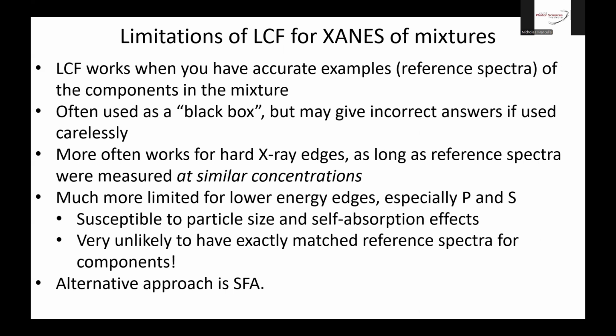So getting back to XANES analysis, comparing linear combination fitting with spectral feature analysis. Linear combination fitting works when you have really accurate examples of reference spectra of the components in the mixture. Typically, that's done for hard X-rays, and it works fairly well. But I want to caution everybody that it's often applied as a black box. Say, okay, I'll plug this into a linear combination fitting and get a result, and that's the answer. Unfortunately, that's often wrong. So you have to be careful with using linear combination fitting. It's a very good tool, but use it with care. The reference spectra that you use for linear combination fitting should be measured under the same conditions, and especially at the same or similar concentrations. That's one of the keys. That's where it often goes wrong.